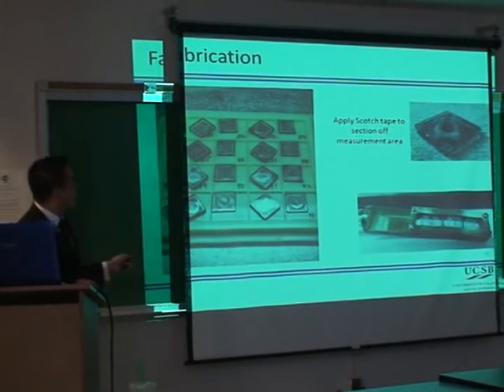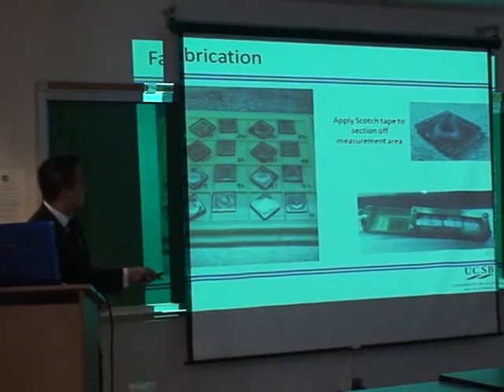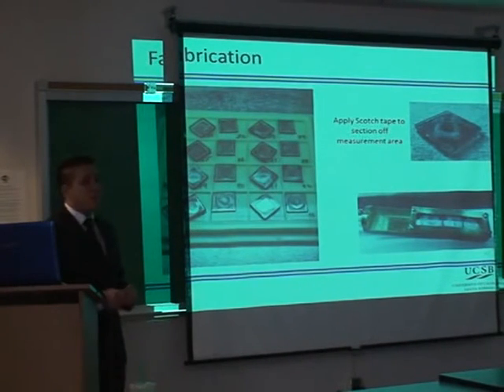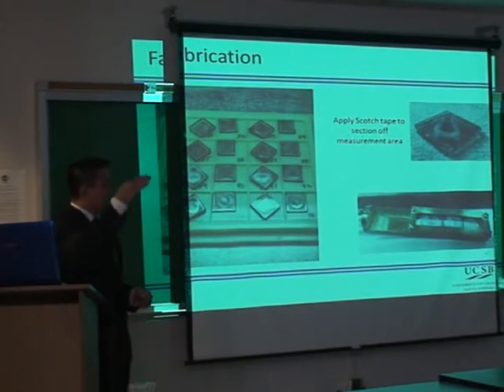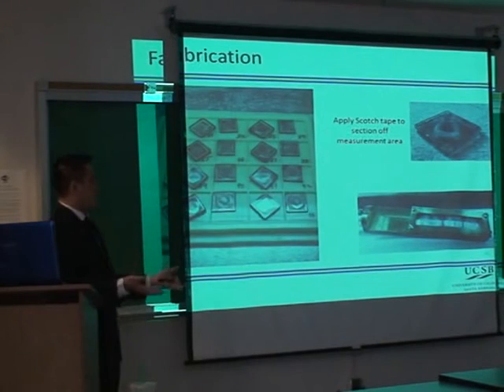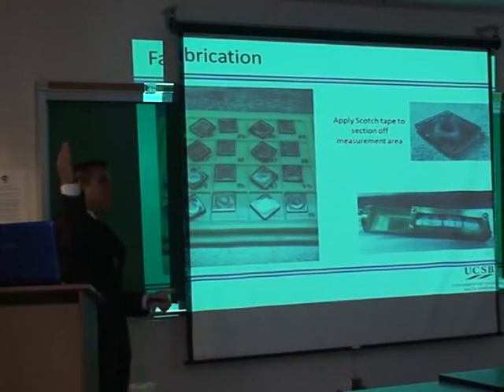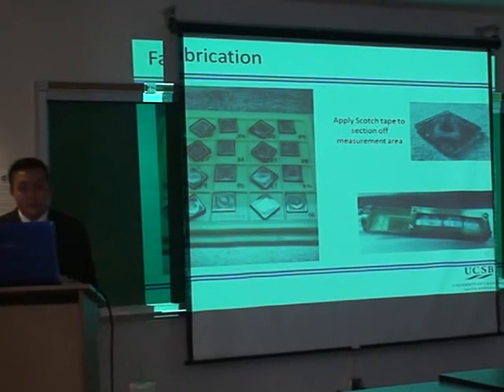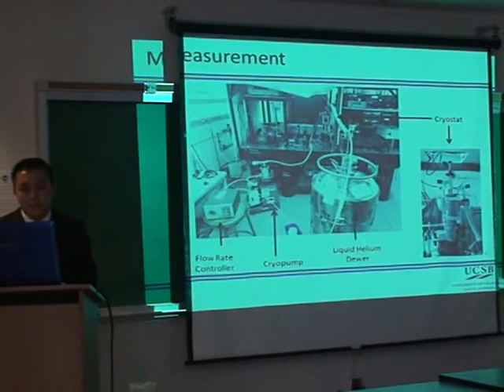So we fabricated a number of films, and then we had this setup where we could measure 3 films at a time. And this was, in a way, a little bit inconvenient, because we have to cool down the temperature all the way down to 4 Kelvin. If we can only measure 3 at a time, that requires a lot of back and forth, going back to room temperature, back to cold, back to room, if we want to probe a lot of different conditions.